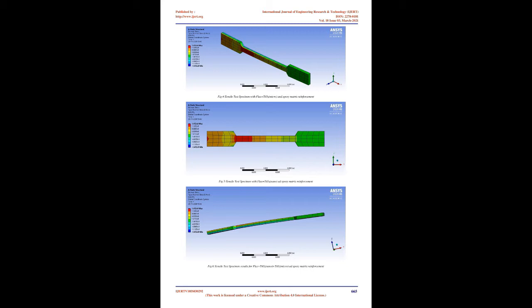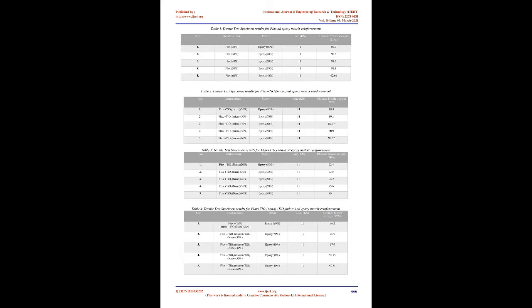The material is modeled using certain assumptions and analyzed for mechanical properties with finite element method software, ANSYS. The composite material is assigned as a unidirectional composite by assuming a few properties that are given below. Some of the assumptions used for the analysis work have been gathered from the literature. Fibers are not porous. The material properties for each of the constituents are assigned as isotropic material for the two volumes. Fibers are uniform in properties with diameter. Interface bonding is maintained between fibers and matrix. Perfect connection between fiber and matrix and no slippage. Fibers are arranged in a unidirectional way and perfectly aligned. Composite material is free from voids.